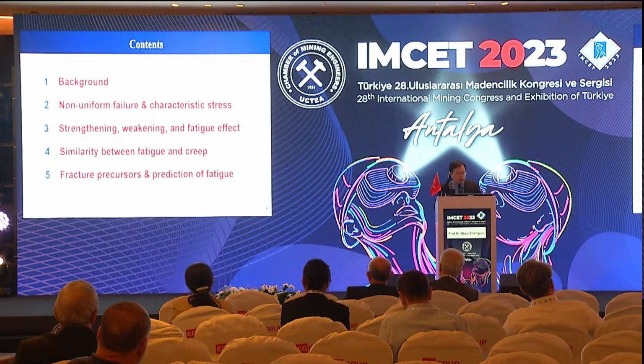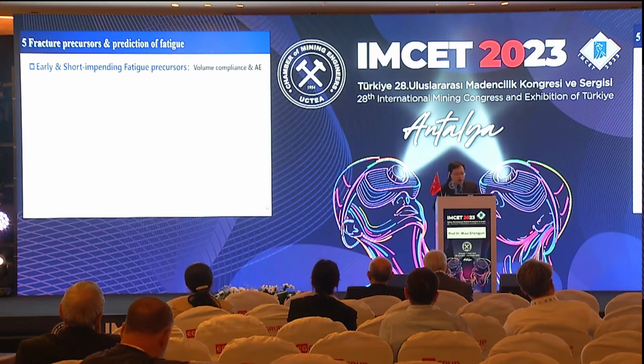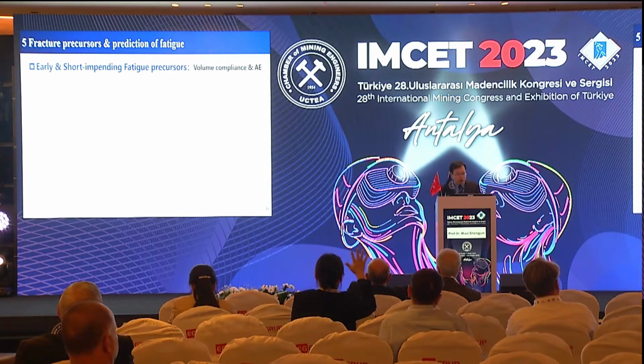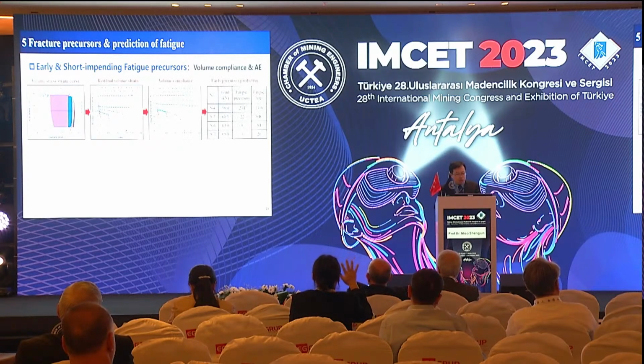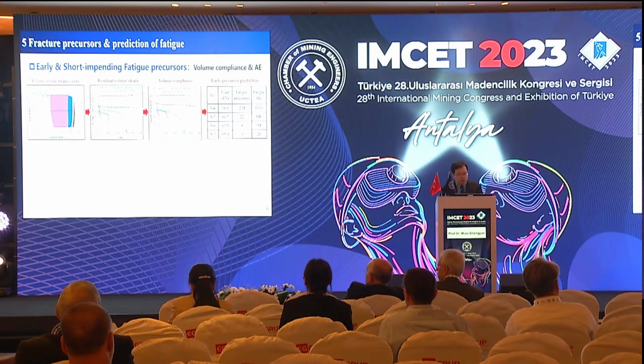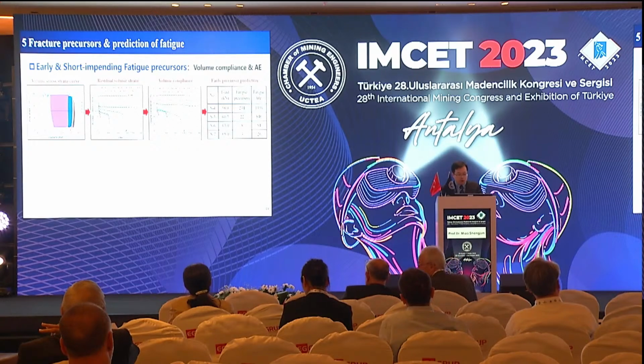Part 5. Based on the previous research on fatigue limit deformation, this part mainly studied fatigue failure precursors of the rock. Here, we observed a common characteristic among the fatigue specimens, where there is a volumetric compliance transition from positive to negative values. In contrast, the volumetric compliance of the specimens that have not undergone fatigue failure remains consistently positive. Therefore, we can consider the transition from positive to negative of volumetric compliance as an early precursor of rock fatigue failure. This indicator can be used to determine whether the rock will fail.